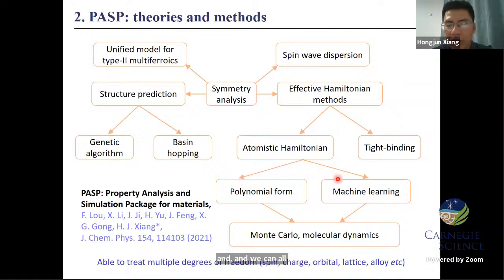Within our package, we include two kinds of potential forms. One is the polynomial Taylor expansion form, and another is the machine learning neural network form. After we construct the atomistic Hamiltonian, we can perform Monte Carlo simulation and also molecular dynamics to obtain the thermodynamic and also kinetic properties of the system. An interesting and important feature of our code is that we can treat multiple degrees of freedom simultaneously. For example, if the system has spin, charge, and also lattice degrees of freedom, we may treat these degrees of freedom in a unified framework.